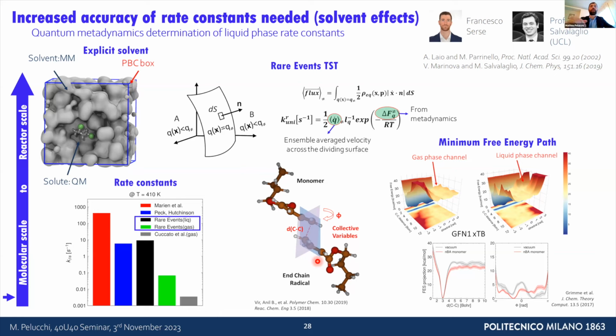Once you've done so, we can compute the rate constant. This is an example for one single temperature of 410 Kelvin. You see how our rare events calculation is in good agreement, within a factor of nearly 2, with the measurement by Hutchinson and co-workers on the polymerization rate, determined using pulse laser experiments.